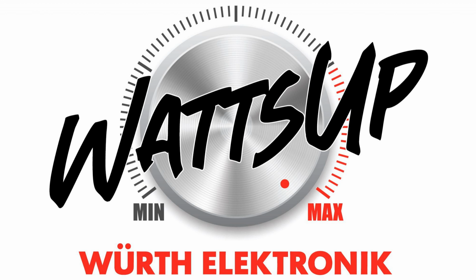Before we get started, we need to talk about the two types of MLCCs. Capacitors are constructed of Class 1 or Class 2 ceramics, and they vary in several aspects. For example, Class 1 ceramics are made of titanium dioxide, have permittivity between 10 and 500, a capacitance range of between 0.3 picofarad and 22 nanofarad, and a voltage range of between 10 to 50 volts.